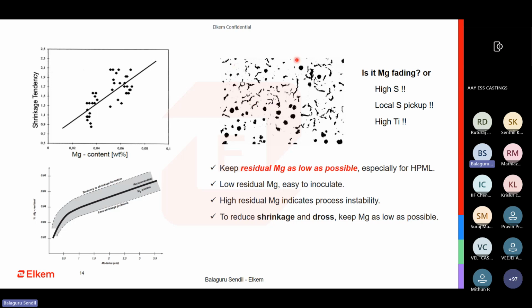When you see this sort of microstructure where CGI has formed, that means the magnesium has faded. A nodule has been broken and has come back to a vermicular structure. This happens when the magnesium is fading. It doesn't only happen because of magnesium fading, it also happens because of high sulfur. When your sulfur is very high, localized sulfur pickup is also possible, because we have sulfur pickup from the sand. It could be on the outer surface of the casting, and sometimes slightly in depth of the casting. So the sulfur is also very important.